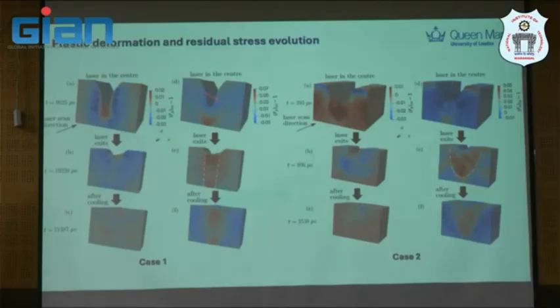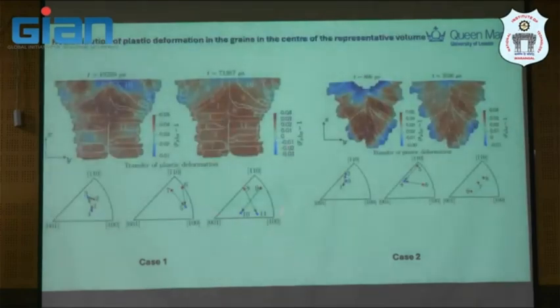laser in the center, and then I think this is the same but at a different time step. After cooling, you actually pile up the residual stress and plastic strain here, in both the full penetration keyhole mode and the conduction mode. You see some residual stress profile here, and then you can map it the same way you did in the experiment that I showed you previously.